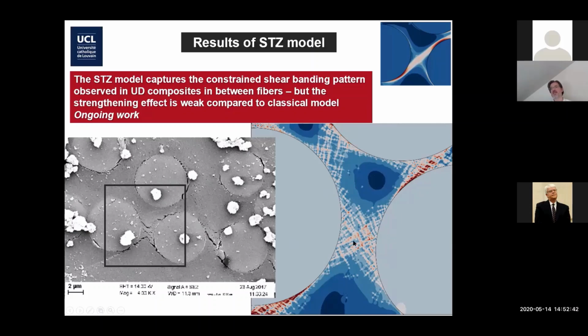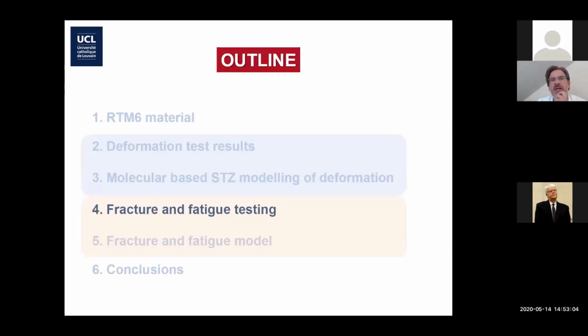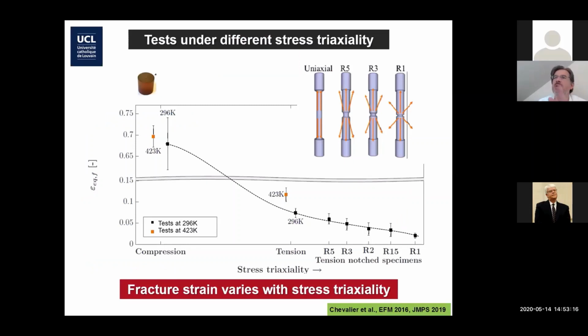The negative message is that we are not seeing much strengthening coming from this model when it's confined in small volumes. And as a matter of fact, we don't get, like in these locations, far field long range effect, which accumulate, which can create the strengthening. So there's still something to understand there. And I'm not saying that with this STZ model, we're solving all the problems by far. A few minutes to show you some pictures about fracture, and I just want to give you perhaps some experimental motivation, and regarding the models, I will just let you read, if you are interested, the papers.